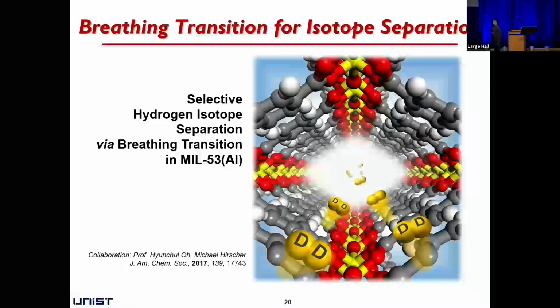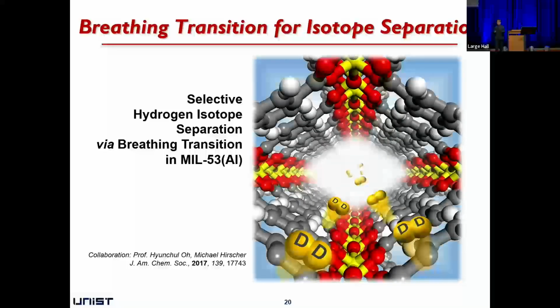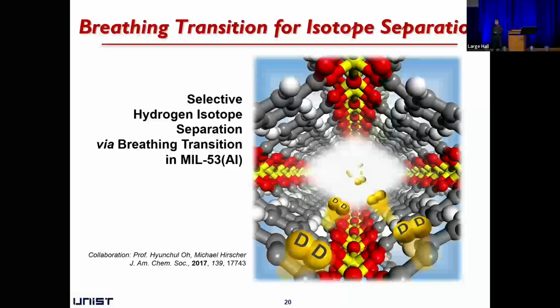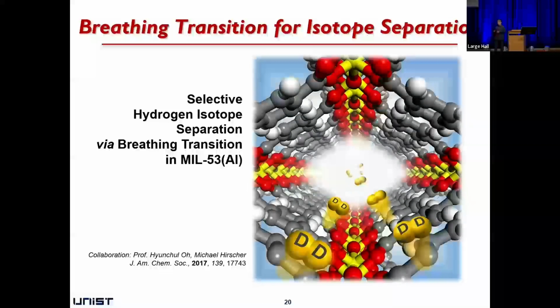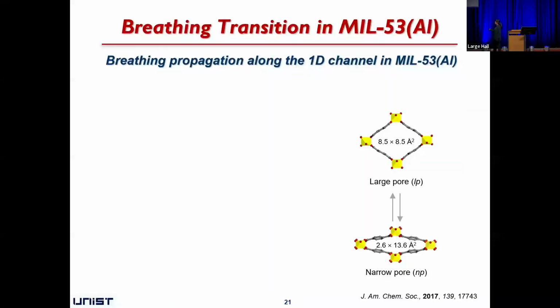So our thought was that to see the kinetic quantum sieving effect, we need a MOF which has a 3 to 3.4 angstrom pore size. But instead of synthesizing this kind of nicely tuned porous material, why don't we use a flexible MOF? So we selected MIL53, and as you know, MIL53 shows a very flexible breathing phenomenon. It can have a large range of pore size, 2.6 to 8.5 angstrom, and it shows a transition between narrow pore and large pore.